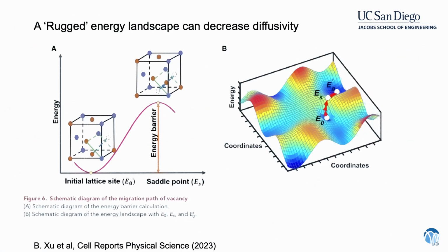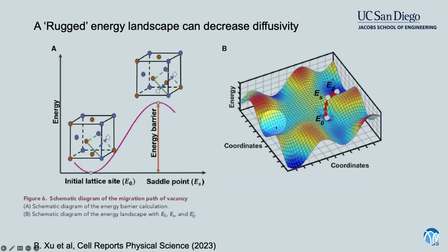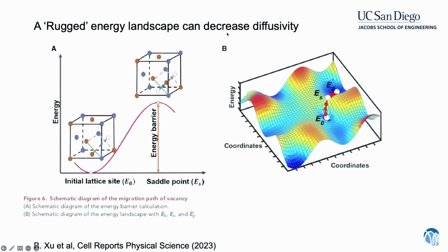Okay. So what's a way that you might be able to reduce diffusion, reducing phase transformation, and making a material, for example, become more resistant to phase transformations? Here's one possible solution. This is out of a paper talking about what people call high entropy alloys. And the idea is that by having a lot of different types of atoms, you no longer have just one single activation energy. You have this rugged energy landscape that makes it more difficult for the atoms to move around. Now, if we were able to design materials with a proper energy landscape, then perhaps we can decrease the diffusion and increase the lifetime of the performance of the material. Okay, so that is one tool we might be able to use.